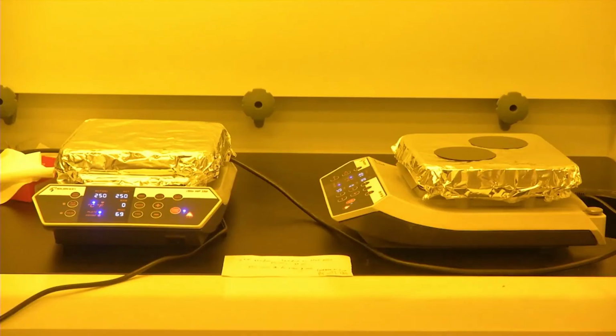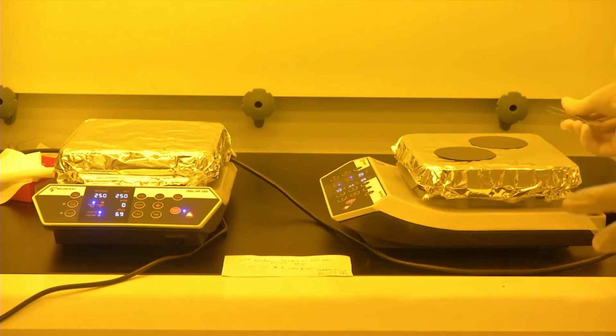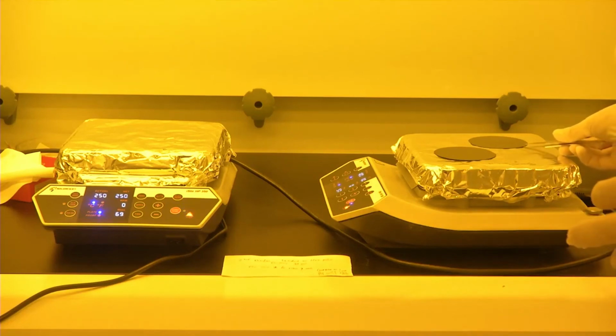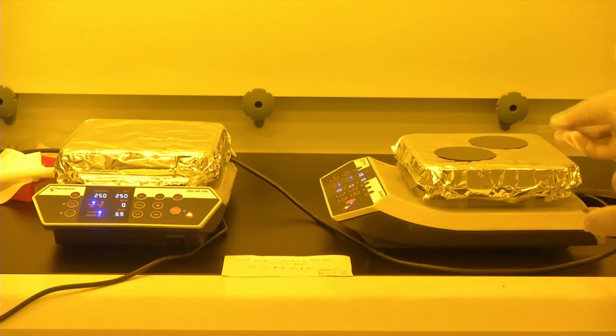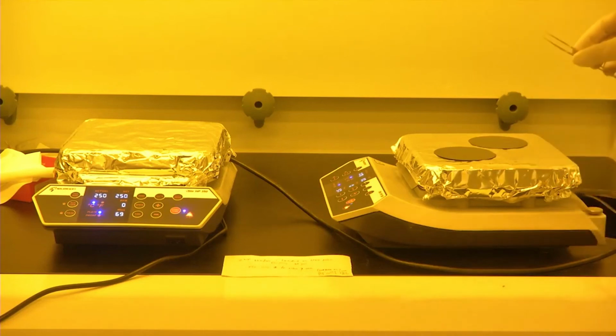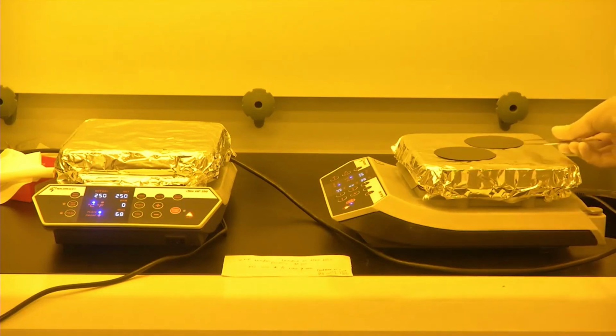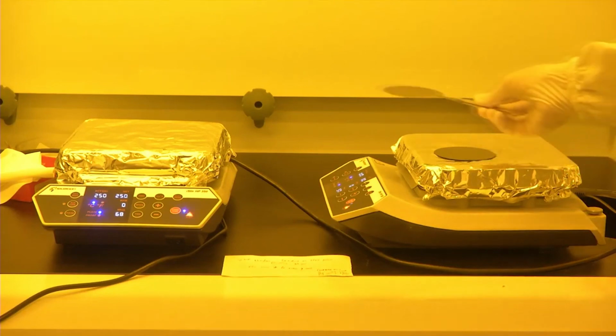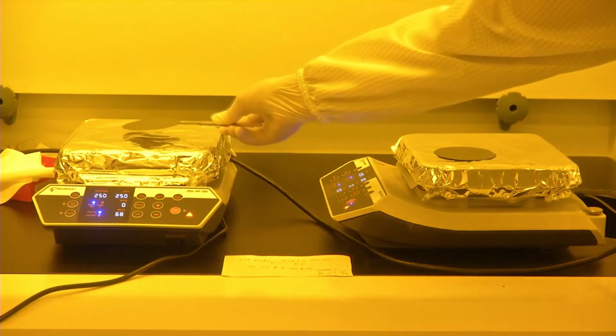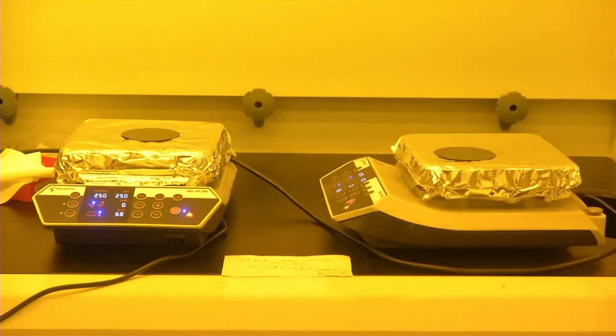So in the process of curing, as we discussed, there are two steps. The first step of curing is done now, which was done at 80 degrees Celsius for 1 hour, and now 1 hour has lapsed. Now we will keep it for curing at 250 degrees Celsius for 2 hours. This will form the second step of curing. So now we will gently keep the wafer on a hot plate which is preheated at 250 degrees Celsius. This will be kept for 2 hours and this completes the curing cycle.